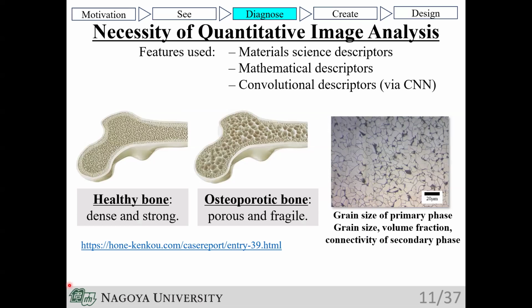Microstructure is not just visual. It must be quantified. For example, we measure the grain size and the volume fraction, and the connectivity of different phases. These can be expressed using descriptors from material science, mathematics, or extracted automatically by a convolutional neural network.